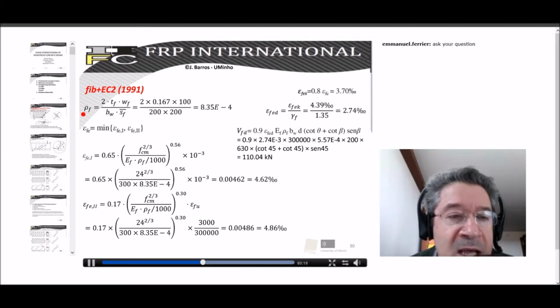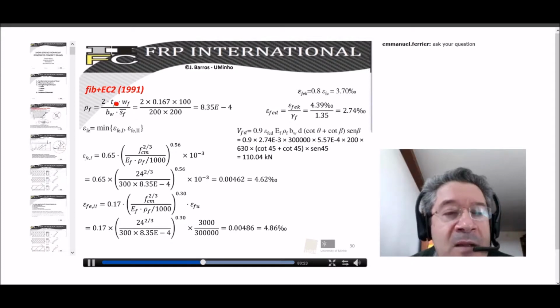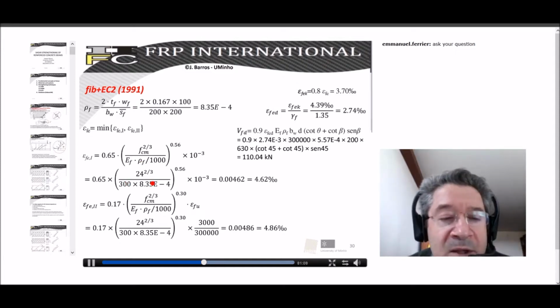This is evaluated from this equation that depends on the thickness, on the width of the strips of CFRP, and on the width of the cross section and the distance between the strips. And then we obtain the corresponding value. To evaluate the effective tensile strain in the FRP, it is the minimum between the two values obtained from these two equations. This is the first equation that depends on the average compressive strength of the concrete, that is 24, and the Young's modulus, and the reinforcement ratio that we have just evaluated. Finally, we obtain a value that is 4.6 per mille.